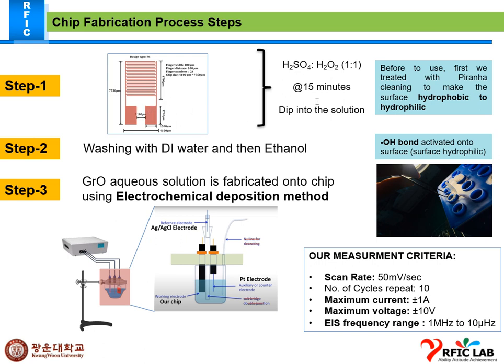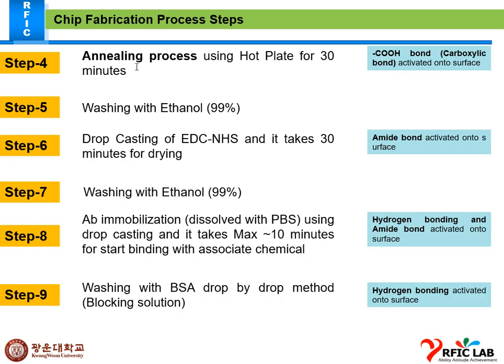And this is the chip fabrication step. First we have to use the piranha cleaning. After cleaning we use DI water and then ethanol until the OH bonds are fully functionalized over the surface, and then the graphene oxide solution is deposited by this electrochemical deposition method. Our measurement criteria are scan rate, number of cycles, which is 10, maximum current and maximum voltage, and frequency from 1 megahertz to 10 microhertz. And afterwards the annealing process that I already did at Korea University after the deposition of the graphene oxide.